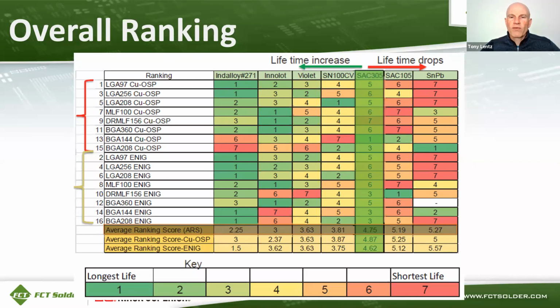So if you look at the SAC305 column close to the right-hand side of this table, to the right of that are SAC105 and tin lead, which performed worse than SAC305. And then to the left of that, we saw a lifetime increase for SN100CV, Violet, Innolot, and Indalloy 271. So Indalloy 271 overall performed the best, but SN100CV was clearly outperforming SAC305 alloy in this summary.